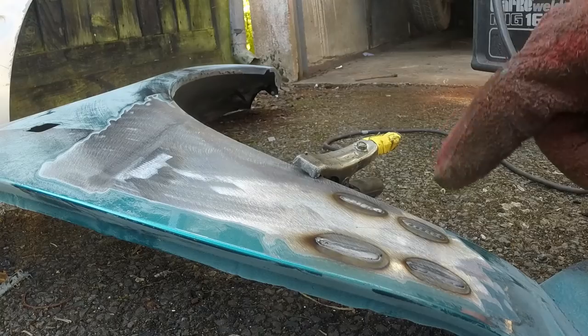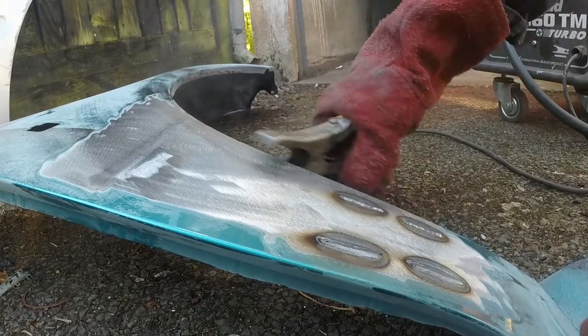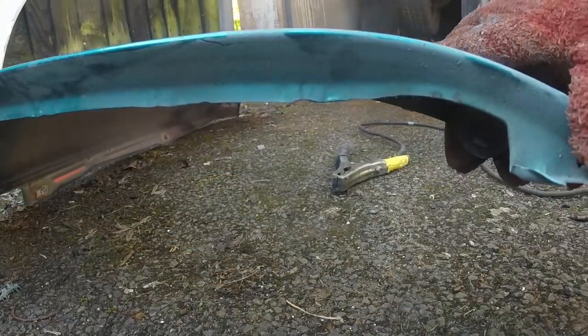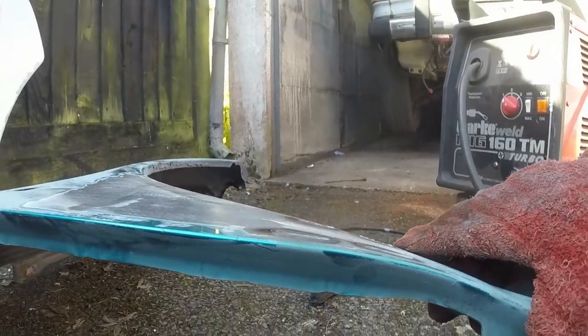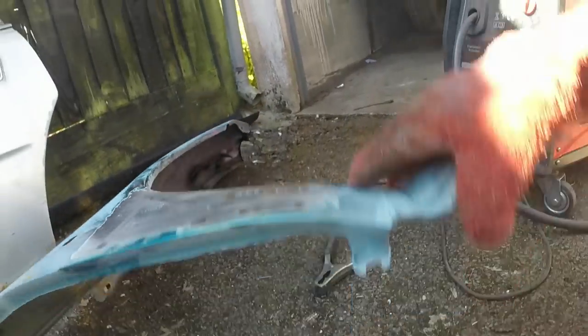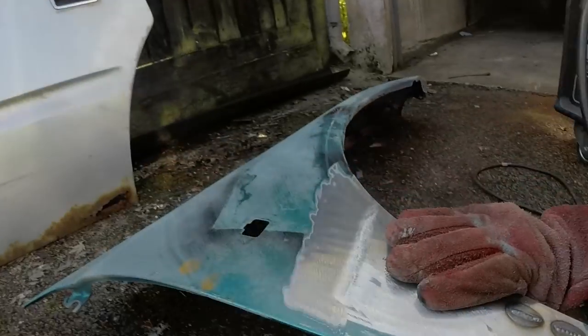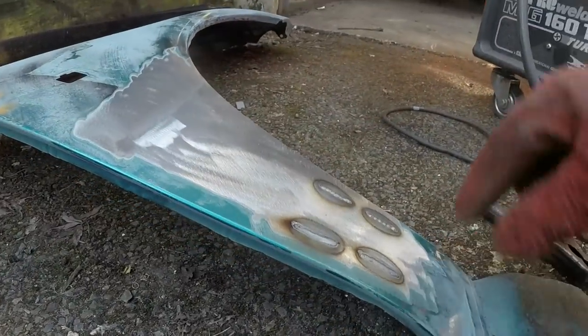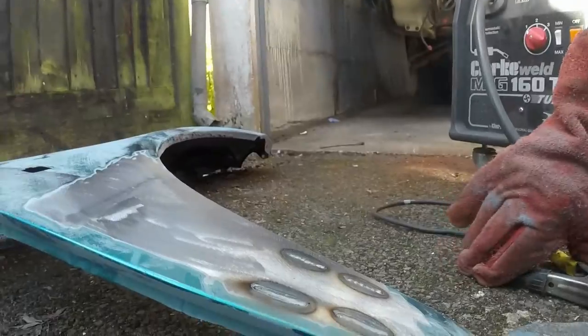So straight away, don't know whether you can see that, but I can. It's starting to get more warping in the panel. You've got more penetration on the back, just slightly, particularly on the seam weld. Not so much difference on the stitch weld, but gravity is taking the weight of that weld pull down and through.